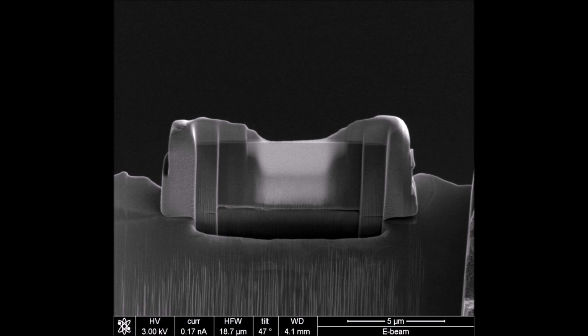So another scenario to consider is that maybe you're not really interested in the surface. Maybe you're interested in the bulk microstructure of your material. Now, obviously, if we have a single crystal substrate like we do here, that's really sort of irrelevant. But if you're dealing with, say, a polycrystalline specimen, then that may be something that's more important and more relevant to consider. Generally, with a single crystal, it's not relevant. Generally, in that case, you are considering the near surface region. But for people who do work on polycrystalline materials, then going into the bulk tends to be more relevant.